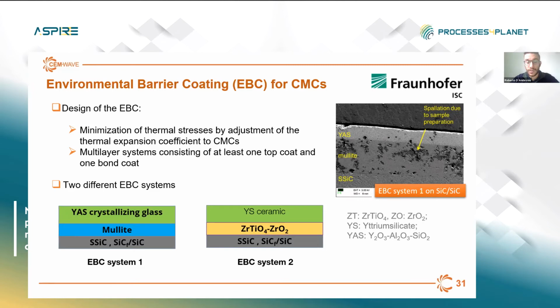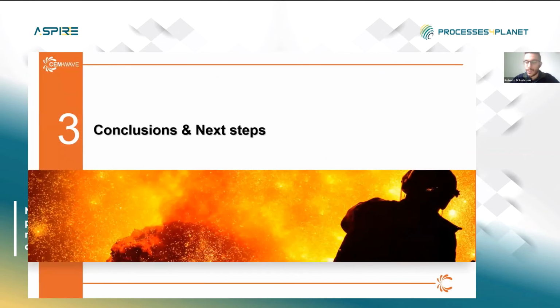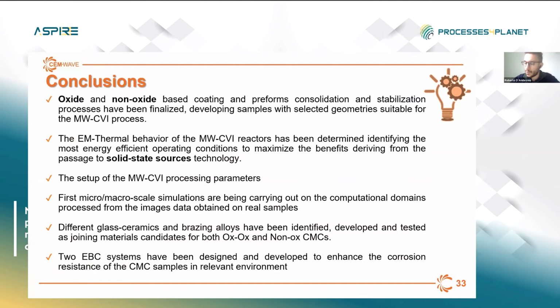Both of those systems were based on a multi-layer system with one bond coat and one top coat, where the bond coat was based on either mullite or zirconium titanate systems, while the top coat was instead based on rare earth silicates. So coming to the conclusion, in the framework of the same work package, our main aim was to make more affordable the application of CMCs for energy-intensive industries.